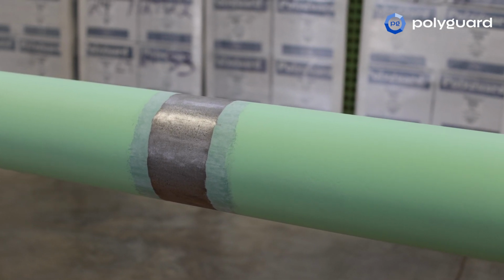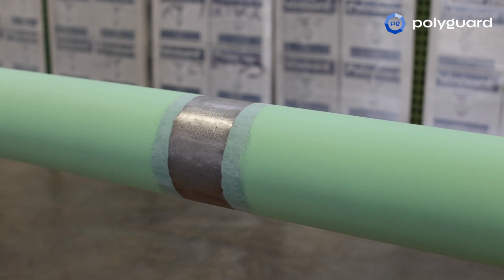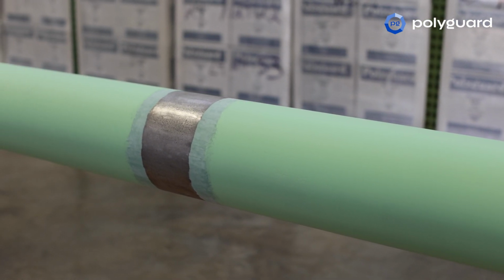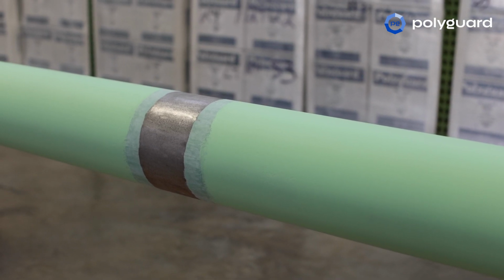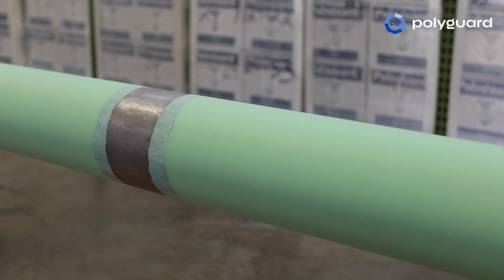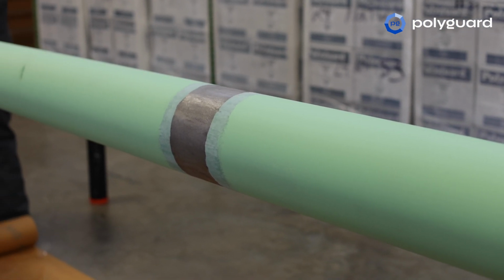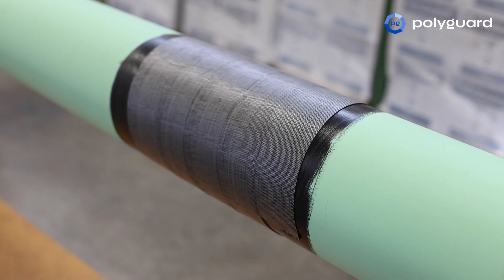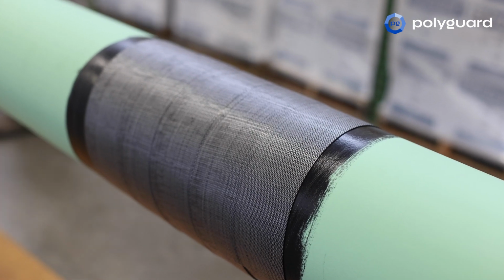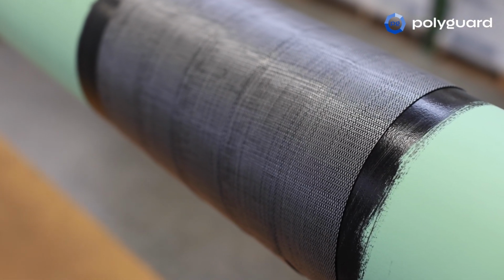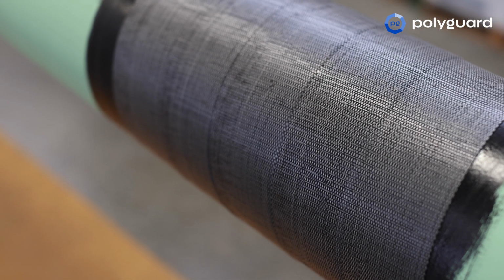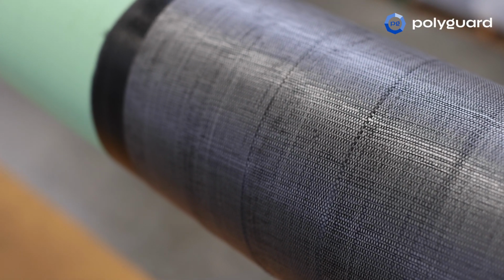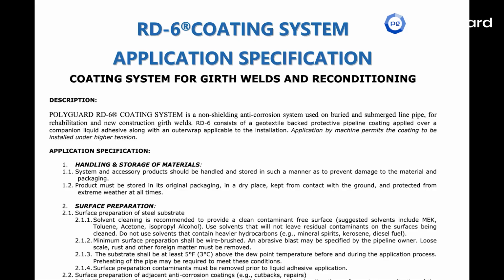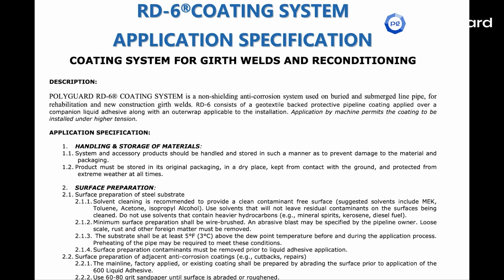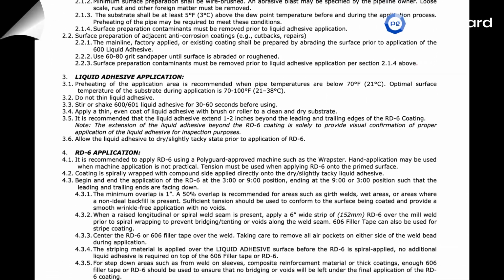When inspecting RD-6 without an outer wrap, Polyguard recommends setting the holiday detector at 4,000 volts for a single layer application of RD-6 and 8,000 volts when applied with a 50% overlap. If a holiday is detected after the application of SP6 outer wrap, increasing the voltage by 2,000 volts for each layer of outer wrap is recommended. For detailed repair instructions, refer to the RD-6 application specification that can be found on Polyguard.com.